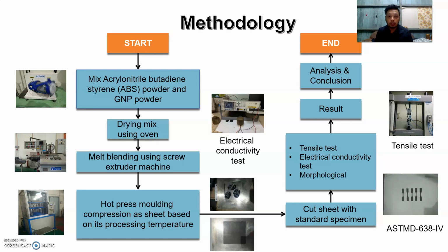Now, methodology. First, I start with mixing ABS powder and GNP powder by using a 3D mixer with a speed of 60 rpm for 1 hour. After that, the mixed powder was spread apart on a tray and dried in the oven at 90 Celsius for 1 hour. After it is dry, blending is done using a single screw extruder machine with feeding zone 180 Celsius, melting zone 180 Celsius and melt pumping zone 160 Celsius.